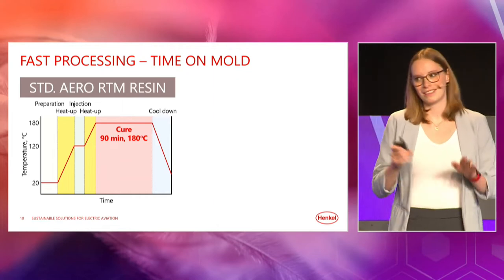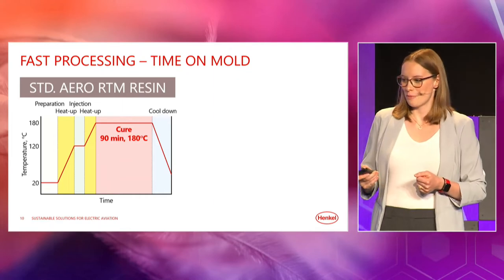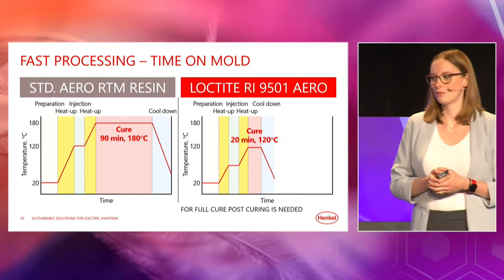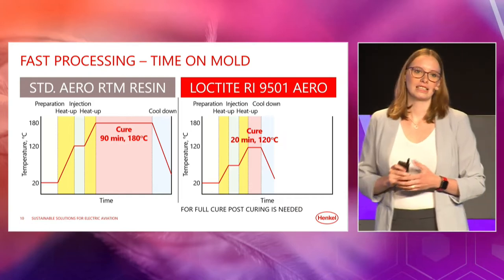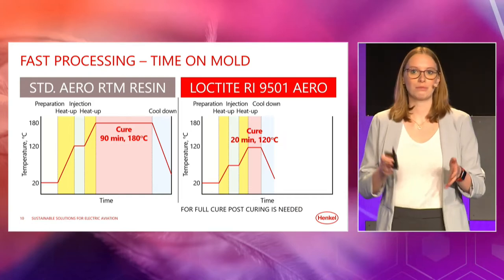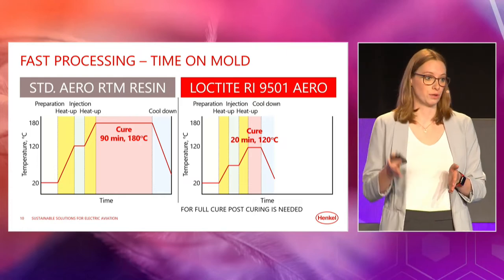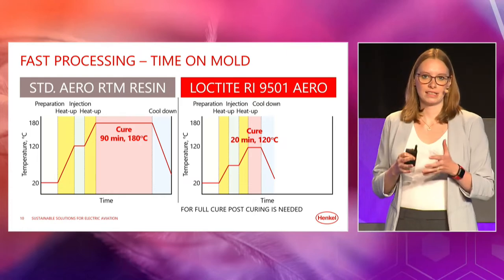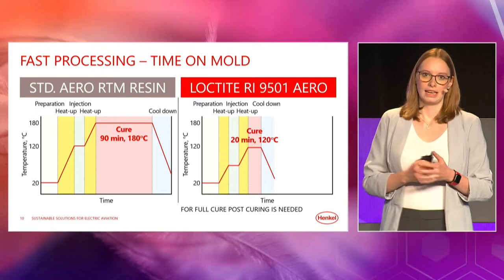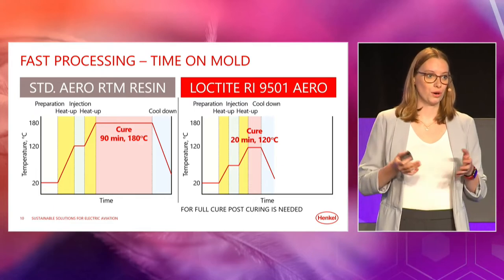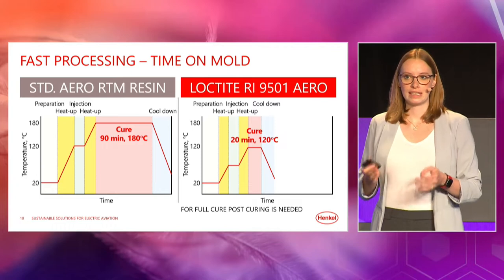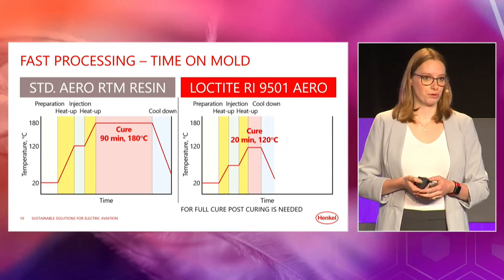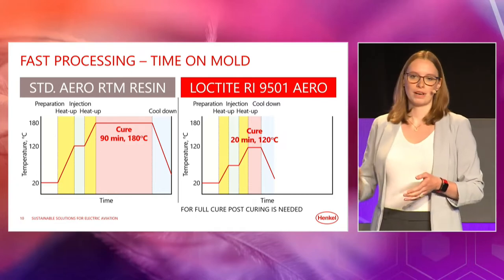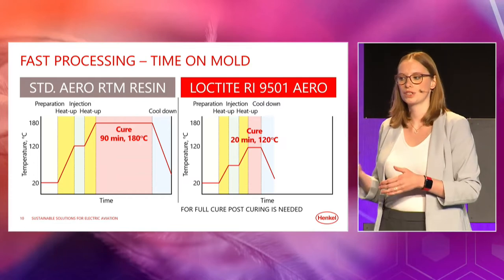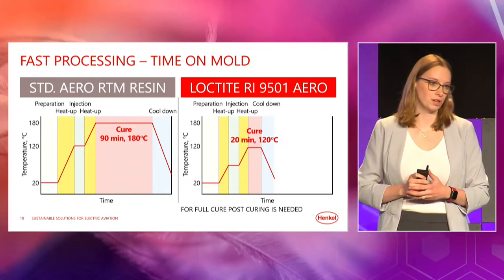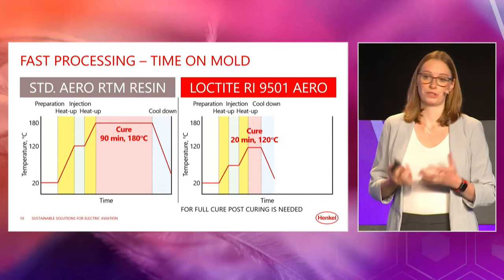And I have to admit, the development was not as easy, but we are there. And the Loctite RI9501 Aero can be injected from room temperature to 40 degrees C. Then everything is heated up to 120. And after 20 minutes cure on the mold, we are already achieving 96% degree of cure. So it's well above the green state. And if we want to achieve 98, 99% degree of cure, we can have a post-cure in a traditional oven.